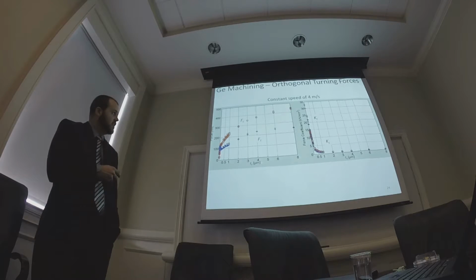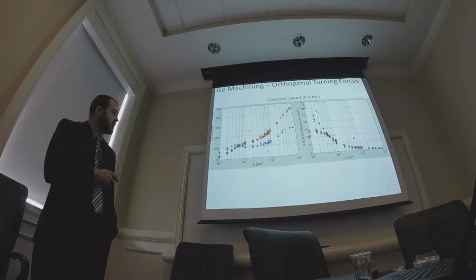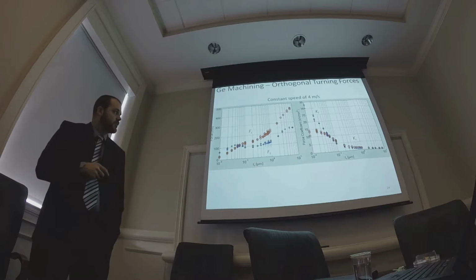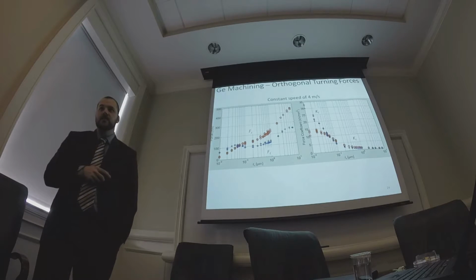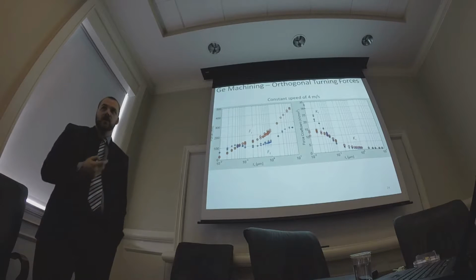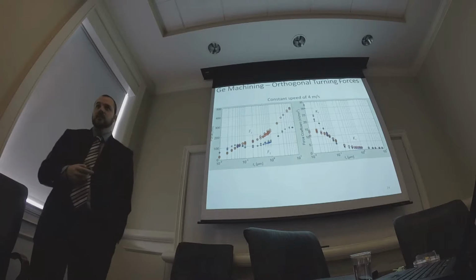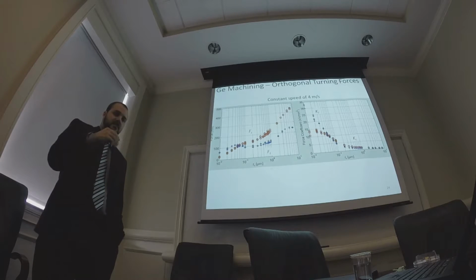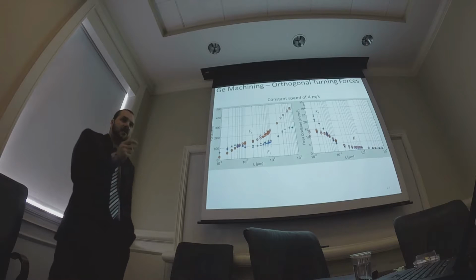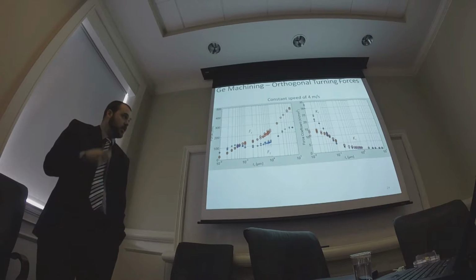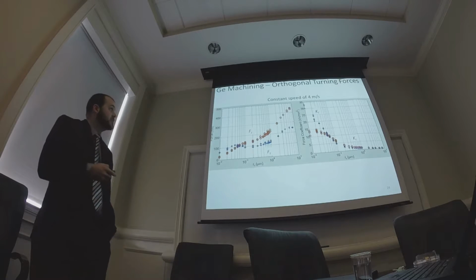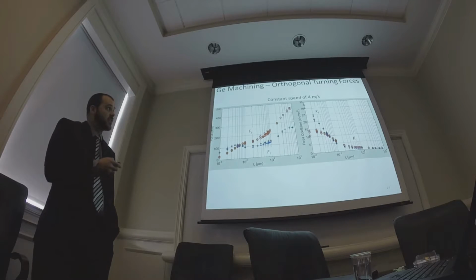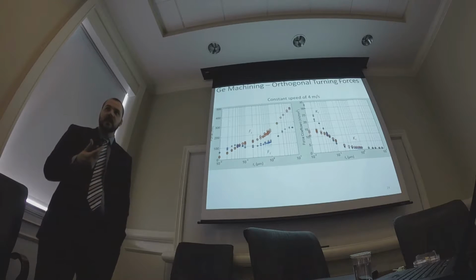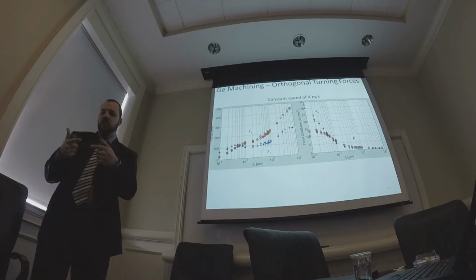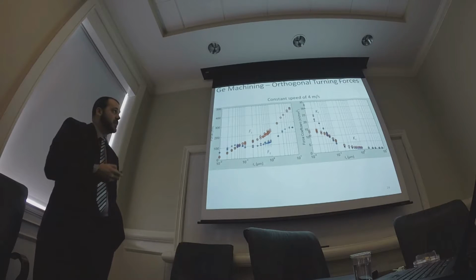It's difficult to see three orders of magnitude, so I put it on a log scale. This transition, when the thrust force drops below the cutting force, I believe is the edge radius of the diamond creating what they call an increased effective rake angle. If the radius of the cutting edge is bigger than your depth of cut, then to the surface it just looks like a big negative rake, and that's why we see this huge spike in thrust. As the negative rake increases, you see a higher thrust force pushing against the tool, meaning it has to work harder to stay in the cut.